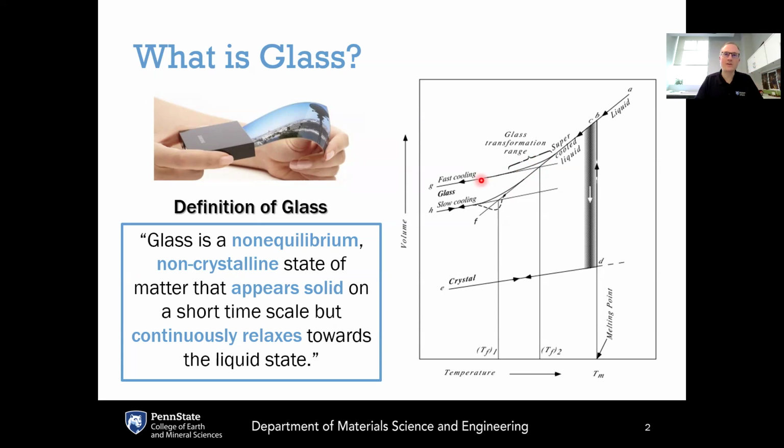Now, another byproduct of the glassy state being non-equilibrium is that the final properties of the glass depend on more than just the chemistry of the glass and the temperature and the pressure. It actually depends on the entire thermal history and, if applicable, also the entire pressure history of the system. For example, if we draw a vertical line through the figure here, what you'll see is that there's two different glasses represented on this plot. One of these is labeled as the fast-cooled glass, and then the other one lower down is labeled as the slow-cooled glass. These glasses both have the same chemistry.